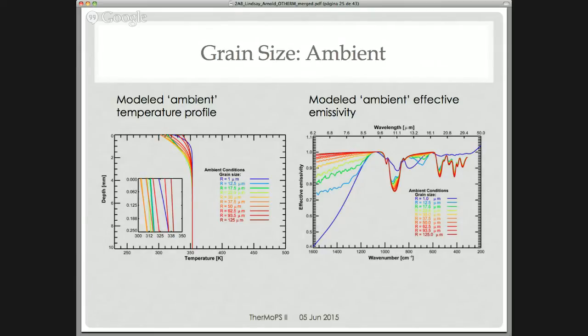And also keep in mind that all of these plots, except for the very end, are for a single grain size, and we haven't really done much with distributions yet. Okay, so first I'll show you our modeled ambient emissivity spectra. I have grain sizes going from 1 micron radius to 125 micron radius, so blue to red. And then this is the model temperature profile.